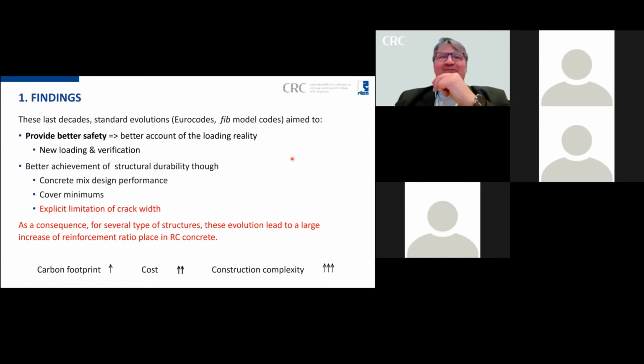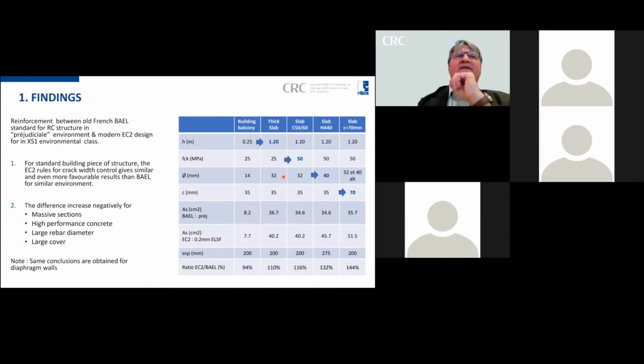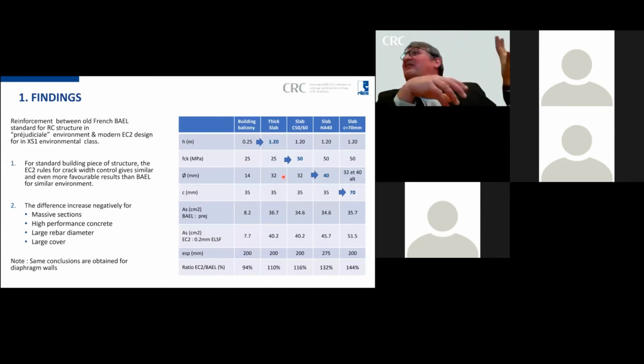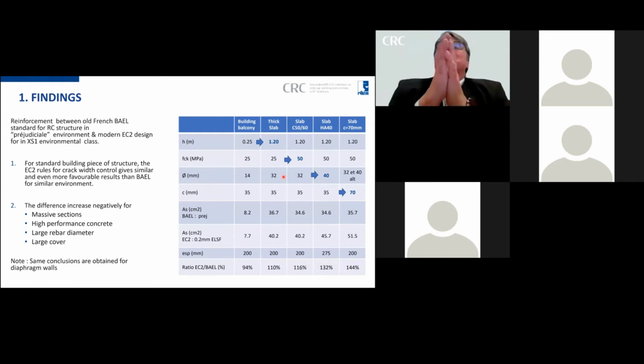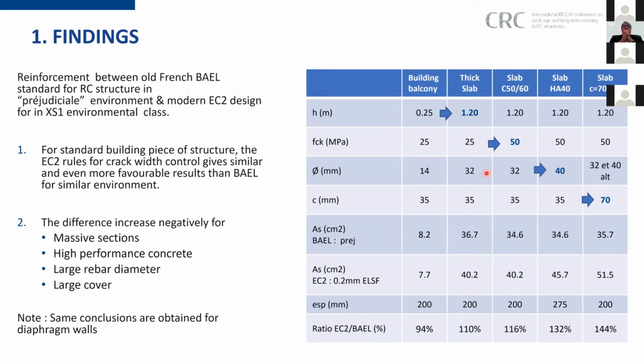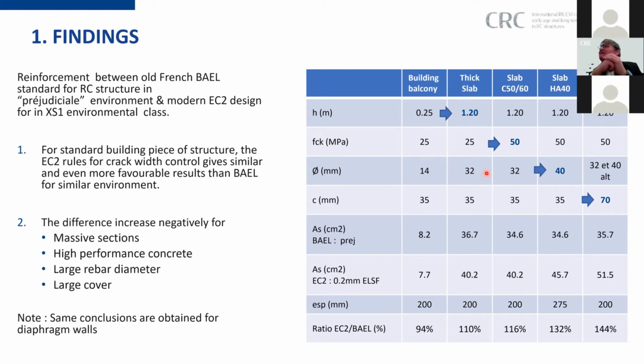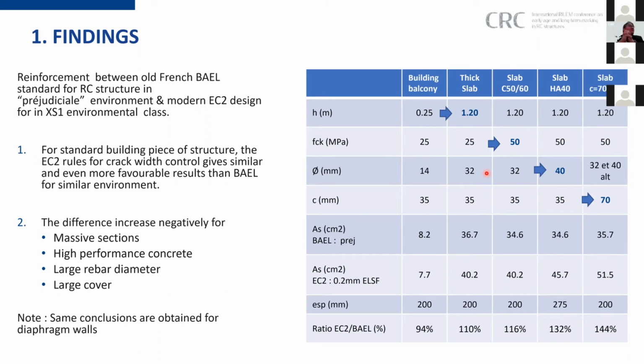And as a consequence, for several types of structure, this evolution leads to a very important increase of the ratio of steel in reinforced concrete. Just have a look and compare the old French BAEL standard in prejudicial environment with the Eurocode 2 standard in XS1 environment. For buildings, it's more or less the same. But if the structure becomes a little bit massive, if you use high performance concrete, if you use large rebar diameter, and if you use large cover, the difference becomes enormous.